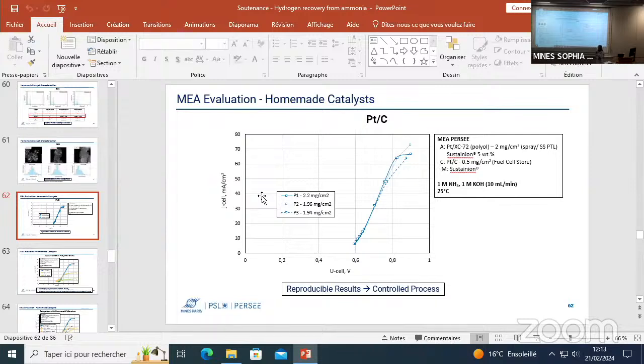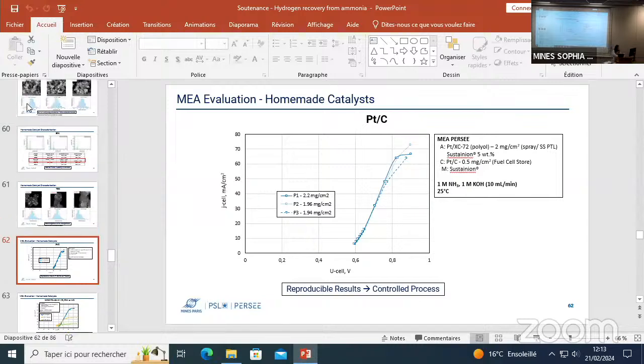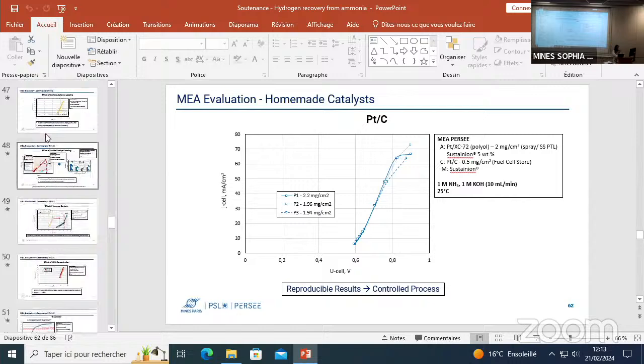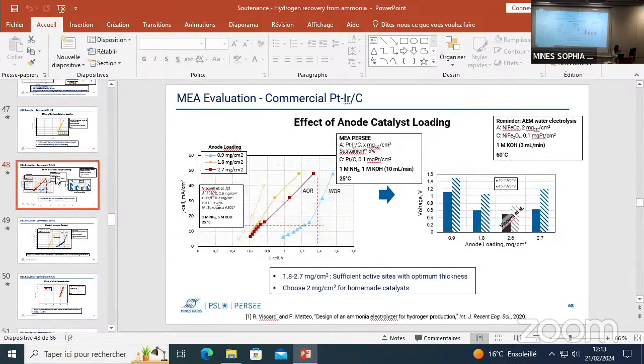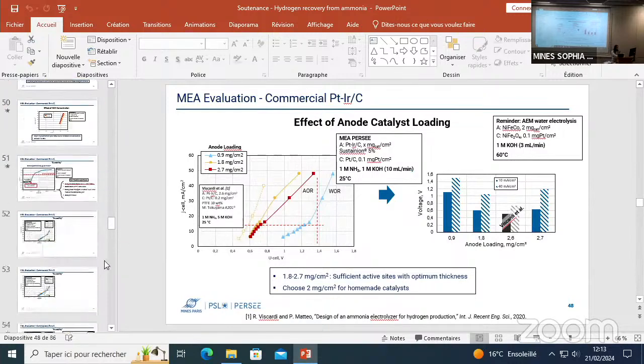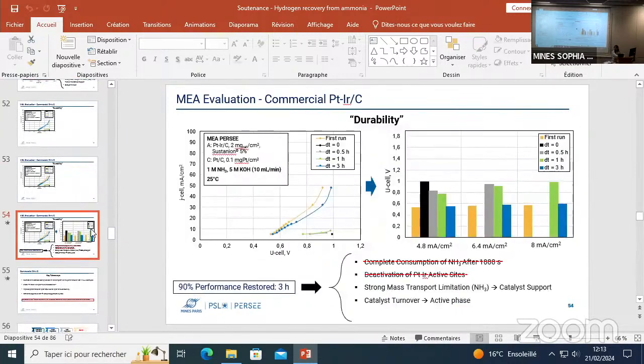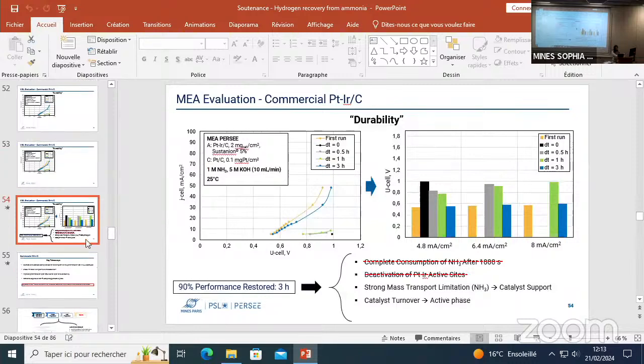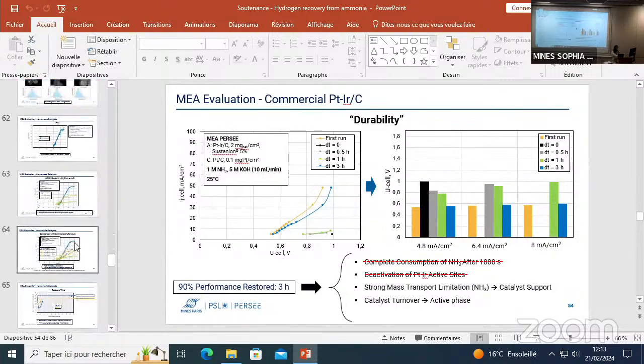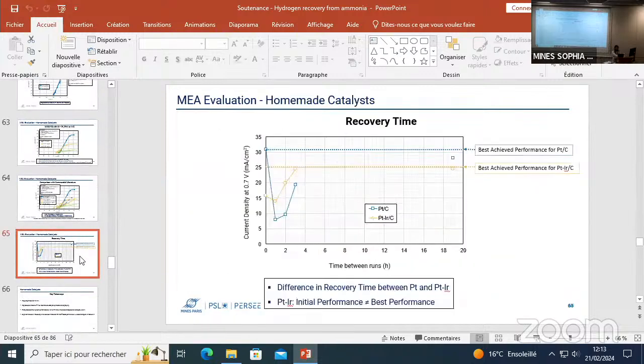I'm not really sure. I cannot tell 100%, because even in the case of a commercial catalyst, let's look at this graph. You can see that I already went very high in voltage, higher than 1 volt. And when I looked at the recovery time, it was 3 hours for platinum iridium, which is approximately the same value that I obtained with the one that I prepared.